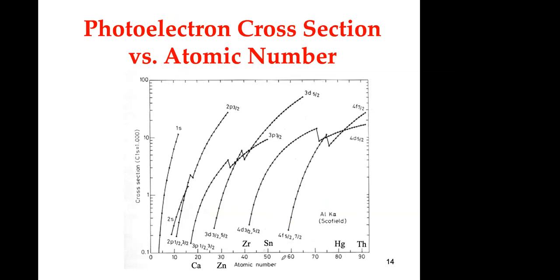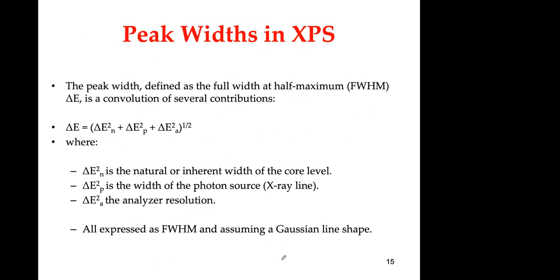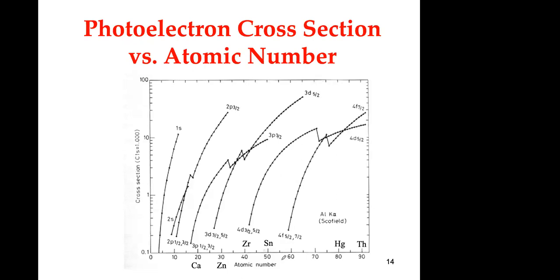Each atom has a different cross-section. Cross-section is sort of like the probability, depending on how many photons reach your sample and how many photoelectrons are coming out. That will be your cross-section. If you get more electrons out with the same energy or number of photons, your cross-section is higher. So the cross-section for the different levels is shown here as a function of the atomic number. Different elements have different cross-sections, and this graph or data is for an aluminum K alpha X-ray source.